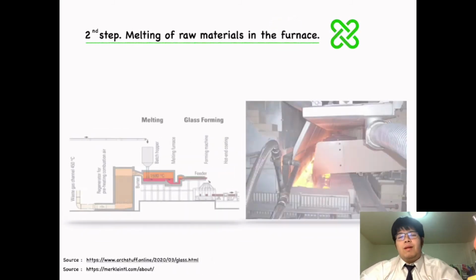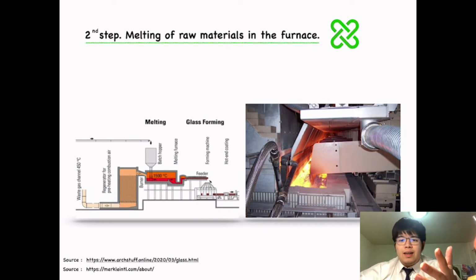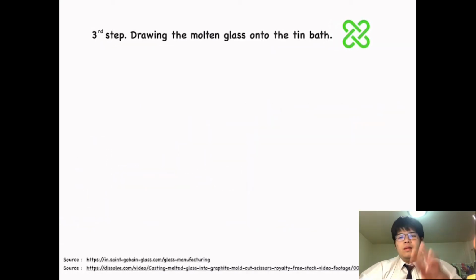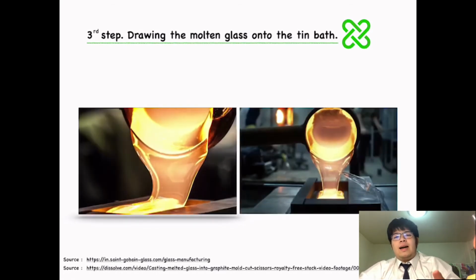Second step is melting of raw material in the furnace. The batch raw materials pass from a mixing silo to a 5-chamber furnace, where they become molten. Temperatures in the furnace reach up to 1600 degrees Celsius. Third step is drawing the molten glass onto the tin bath. The molten glass is then flowed onto a bath of molten tin at a temperature of about 1000 degrees Celsius. It forms a ribbon which is normally between 5 and 6 mm by suitably drawing the glass, through a complex process involving top roller machines.